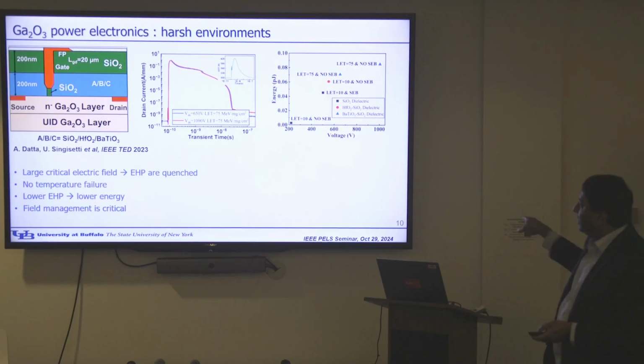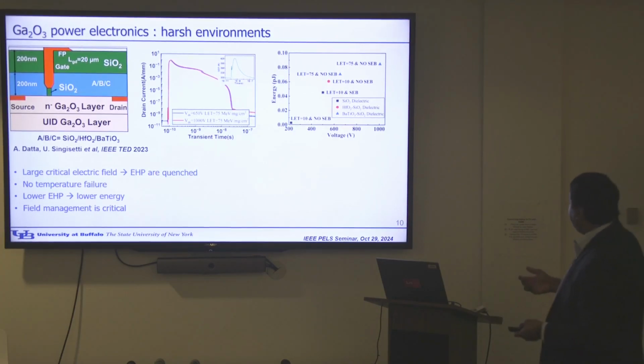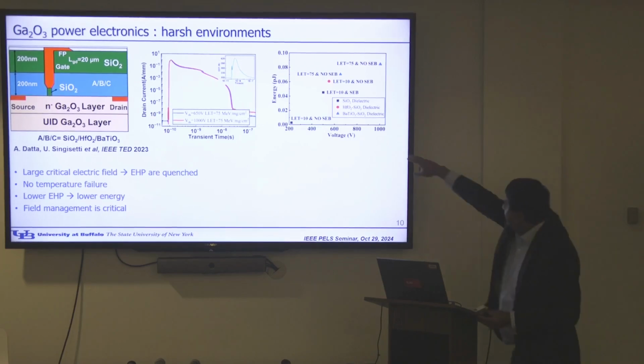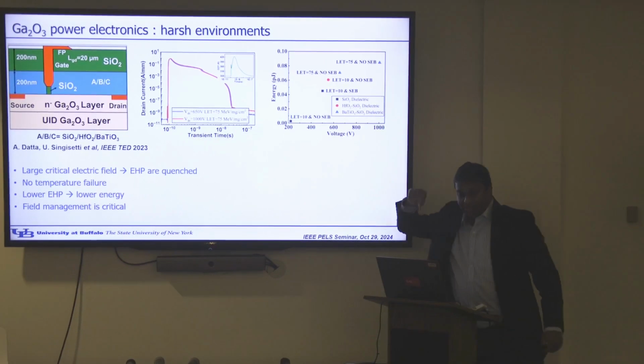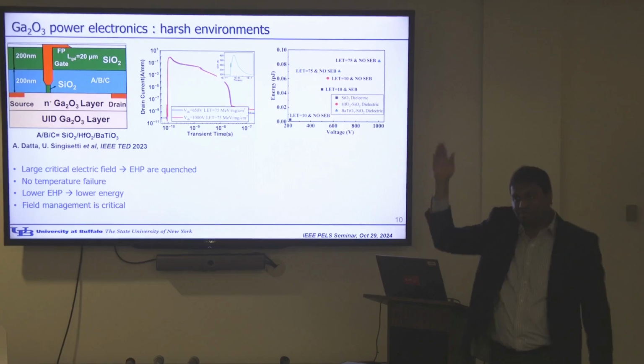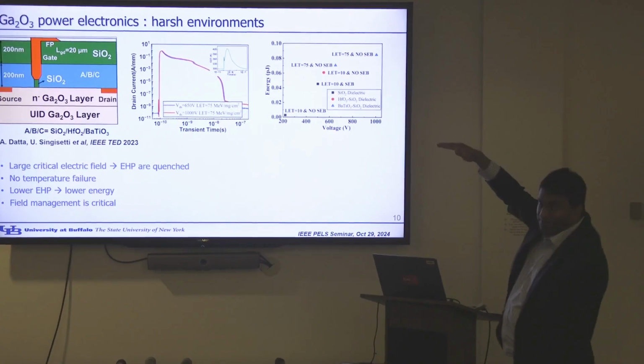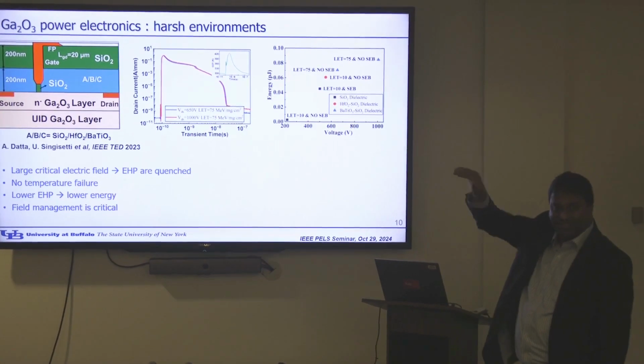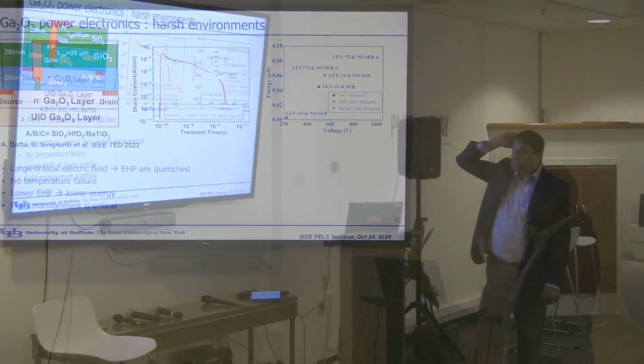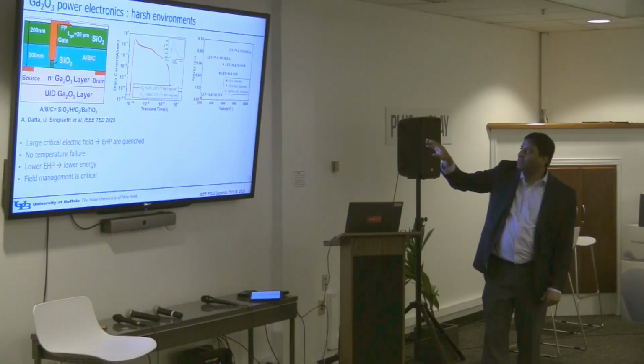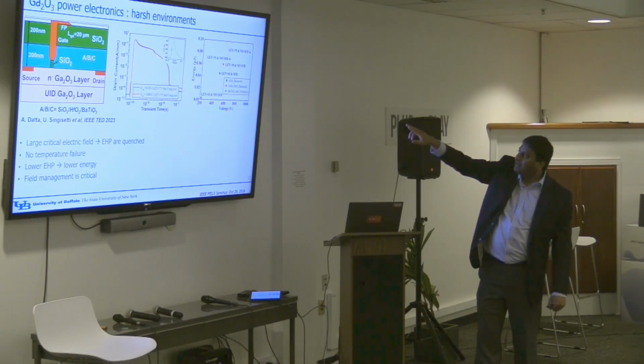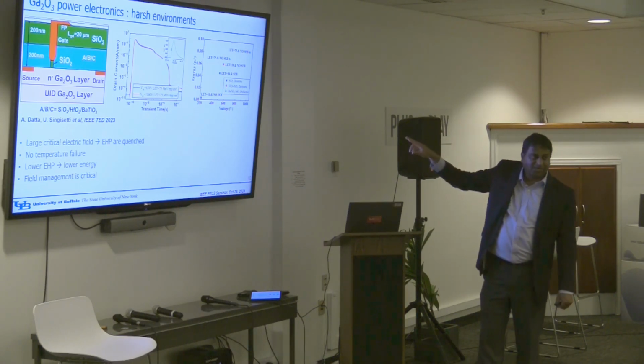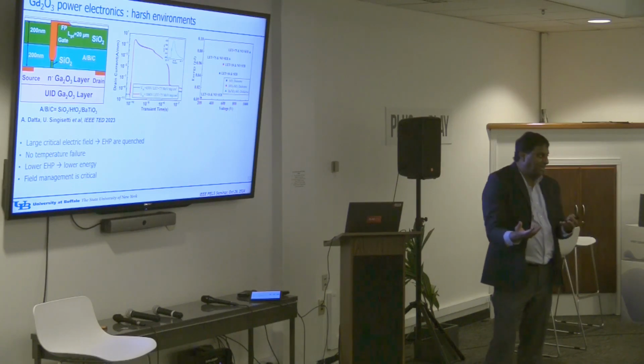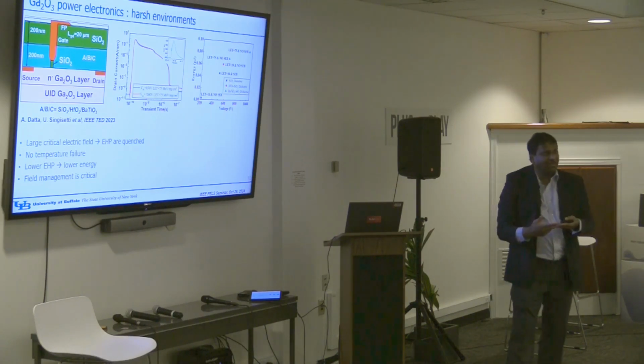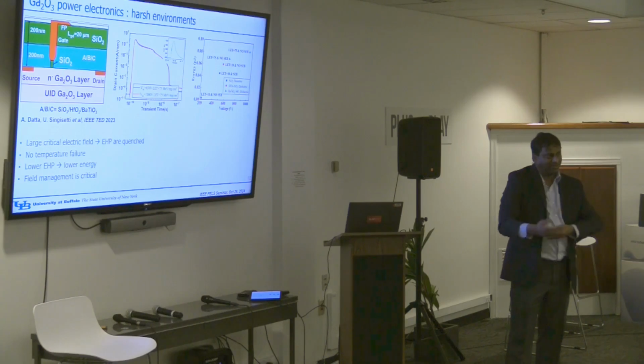So if it comes down to the background level, then there's no failure, right? On the right side, you can see there are some which say SEB, single event burnout. In those simulations, the current does not come back down; it just stays up. This is kind of avalanching; it just locks in there, right? Those are failures. Now, what was interesting here was that you can see the inset on the top there, the temperature, right? Temperature rises, comes down again. So whenever there's a failure, you can have an electrical failure, you can have thermal failure or electrothermal failure, right?